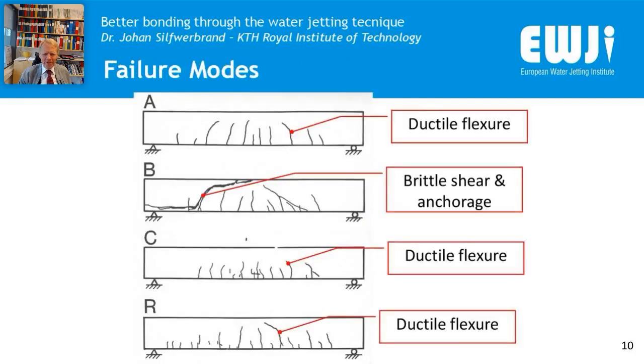And you can see that the beams were simply supported, and we had reinforcement in the bottom. And then you can see that it was quite interesting that we received various types of failures. So on the A, where we had a very thin overlay, observe that the overlay is in the bottom. So we made the beams upside down, which is more interesting for the purpose here.